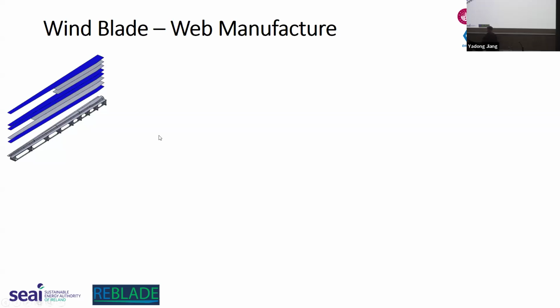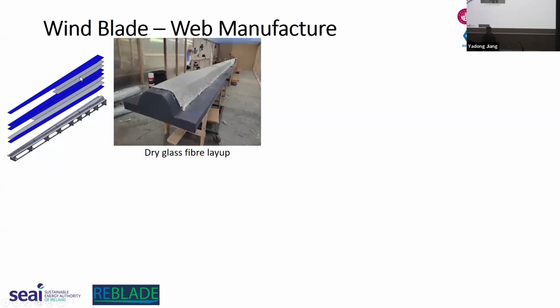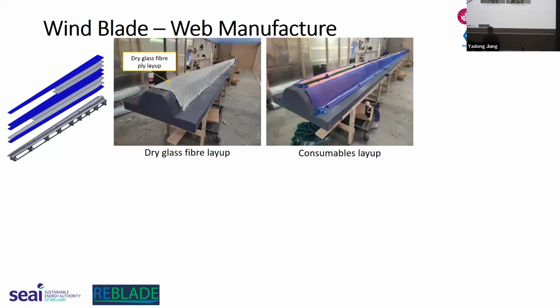The CAD model on the right shows the number of plies that we laid down onto the mold. So they're a mixture of triax in blue and unidirectional glass fibers in gray. So you can see in this image here, the dry glass fiber ply layup has started. And the next image, the consumable layup. So we can see the peel ply, which is white, and the pink is a release film, and then the blue is your distribution fabric. Same as before with the 5 meter demonstrator.